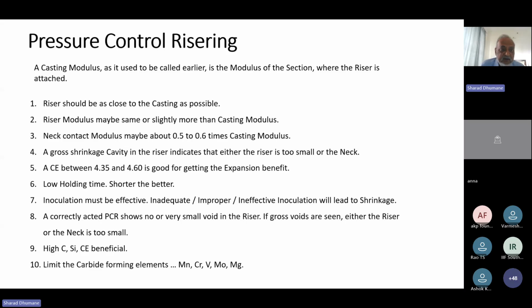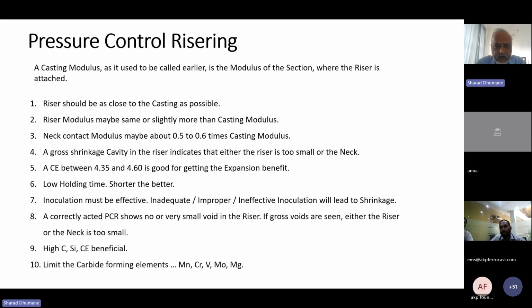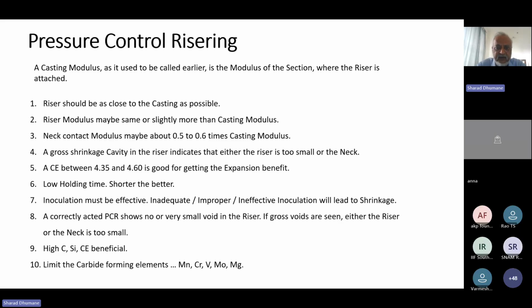For that process to happen, the neck modulus should not be more than 0.6 or 0.7 times casting modulus. When neck modulus is higher, there is quite a chance that the neck will not freeze in time, and it will allow the expansion and the subsequent metal going into the riser. And then when the solidification is getting completed, it solidifies and doesn't allow the riser to fully compensate the shrinkage. So if we keep the neck modulus of the correct size, correct design, then we are able to take the benefit of the graphitic expansion fully, and compensate the solidification shrinkage in casting sections fully.